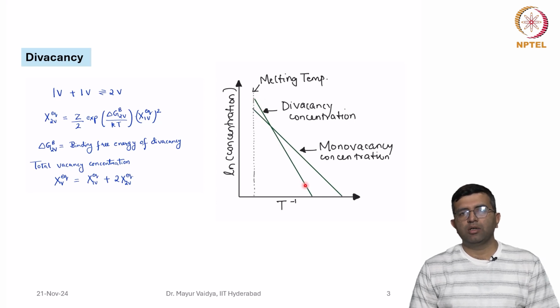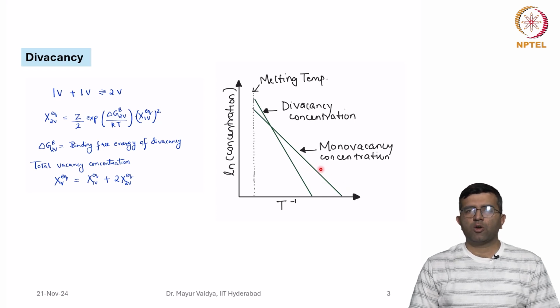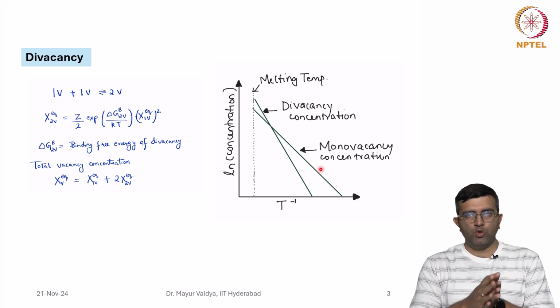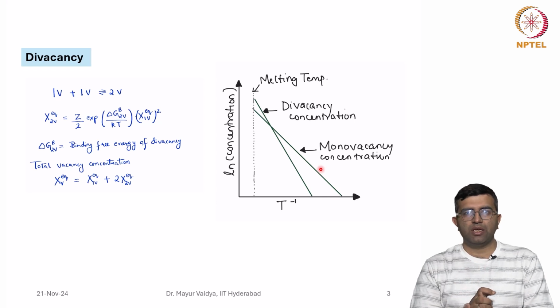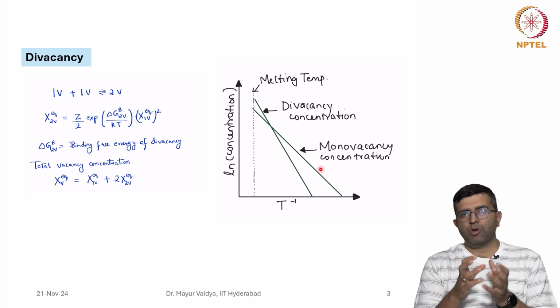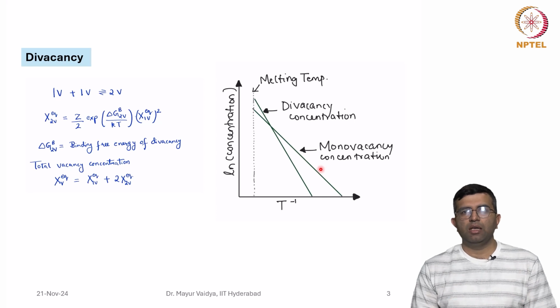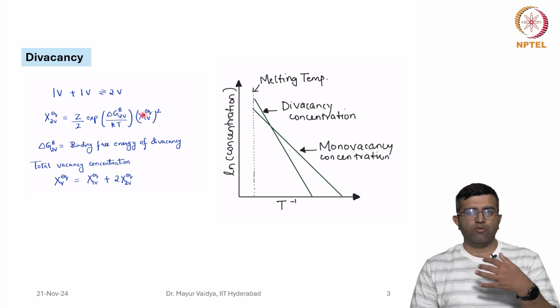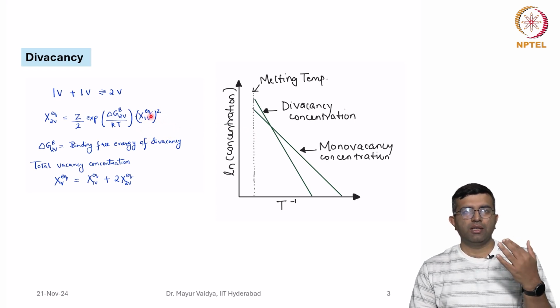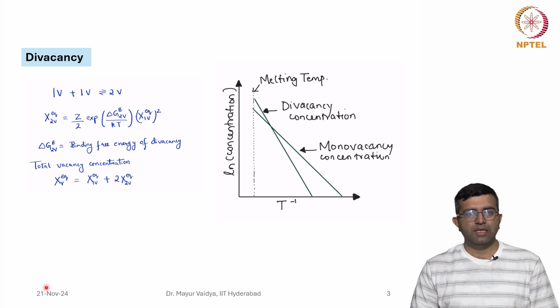Otherwise, as you go to lower temperatures, the mono vacancy concentration is more dominating. In quite a lot of diffusion mechanisms, or when we understand the problems, we predominantly talk about the mono vacancies. Divacancies are still lesser in number. You can imagine also that the mono vacancies are on the order of 10 power minus 4. Then the square of it is already a lesser number.